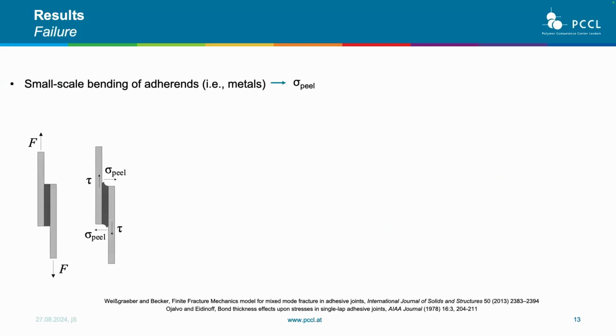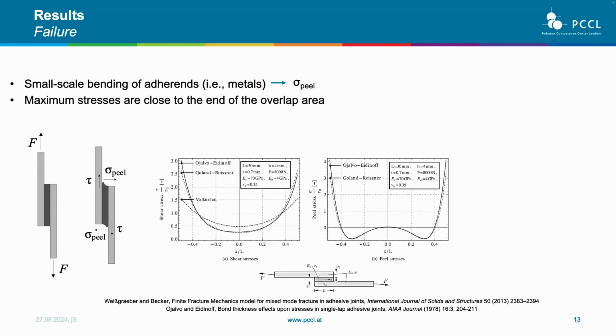But we looked at what happened in more detail during the failure process. During the loading, the adherends of the metals bend slightly, and this creates a peeling stress. This peeling stress tries to go in this direction, so we do not have a real full mode 2 failure, but a mixed mode 1 and 2. This was known in literature, and in general, the maxima of the stresses are at the end of the overlapping area here, as you can see, the maxima of both shear stress and peel stress.